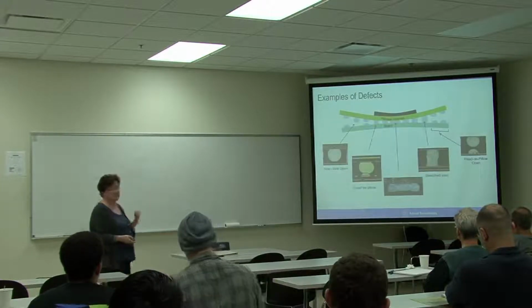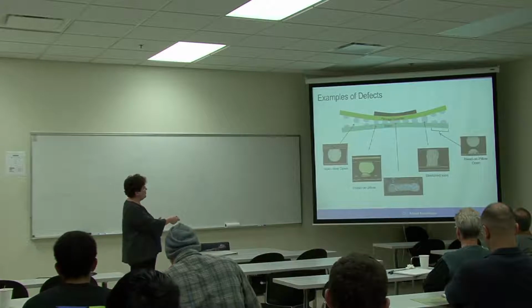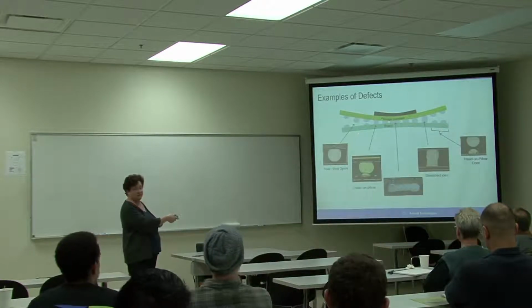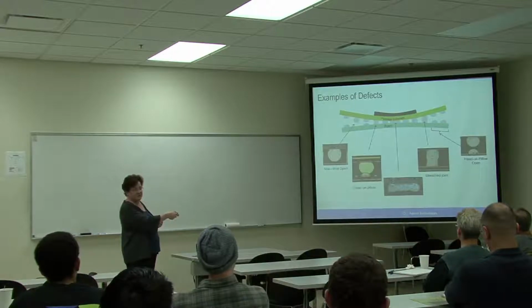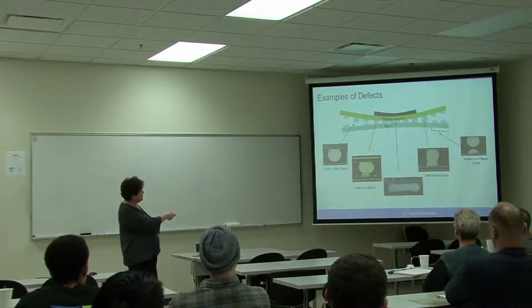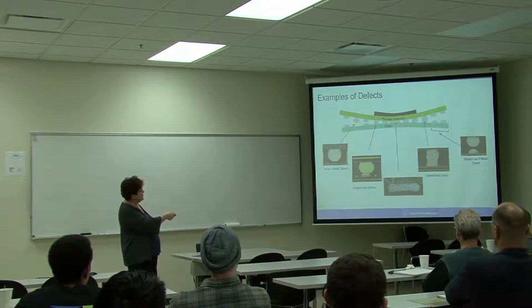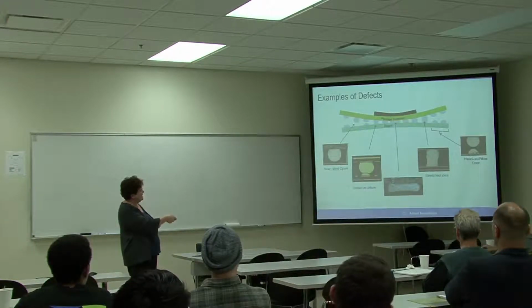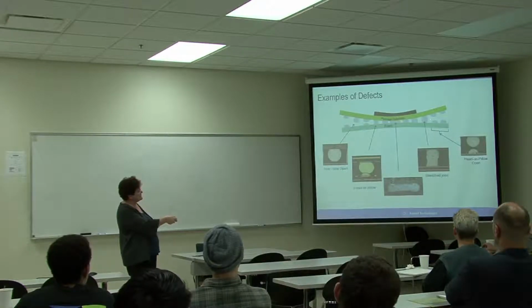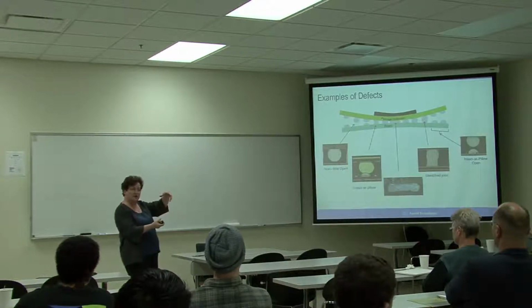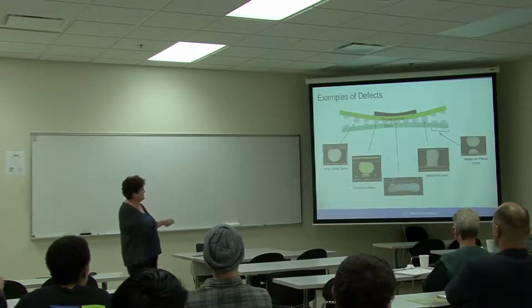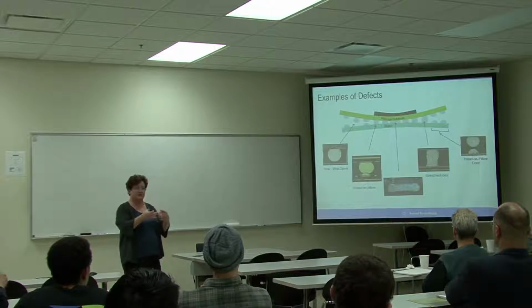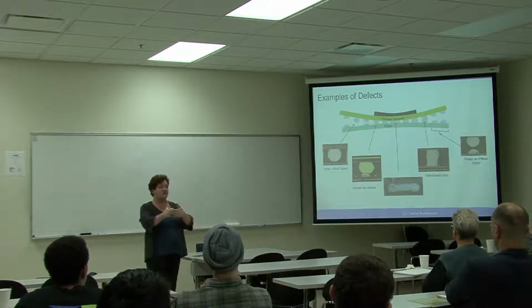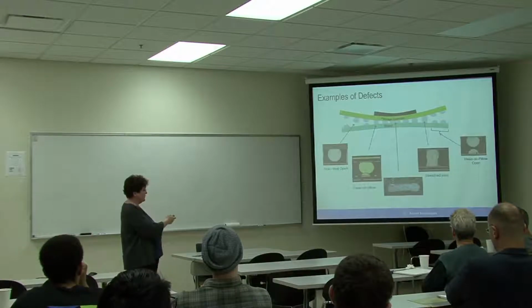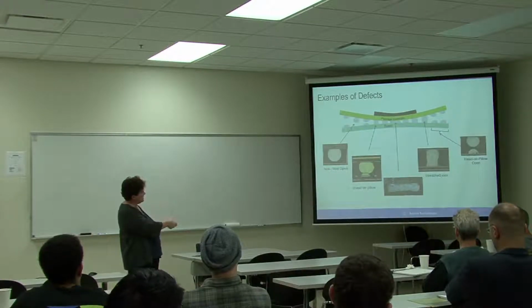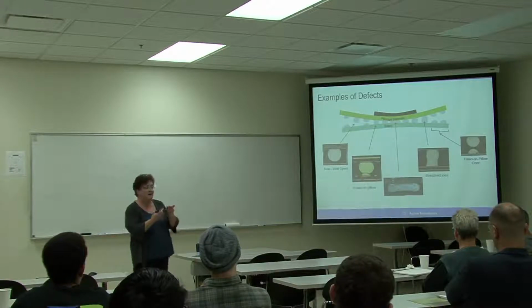So here's an example of defects. Here we have a slightly warped board in the frowny direction, and we have a very warped package in the smiley direction. And what you have then is opens, total opens here. You have an open that actually pulled the paste off the pad. You have another open here. You have a stretched joint, so that solder is stretched enough that it's probably not as robust as it should be. You have here a bridge, so it squished the paste together enough that it connected, and you have a short where you're not supposed to have one, so that's not good. And then there's a defect here called head on pillow. So here's the head, there's the pillow, and it never actually wetted.